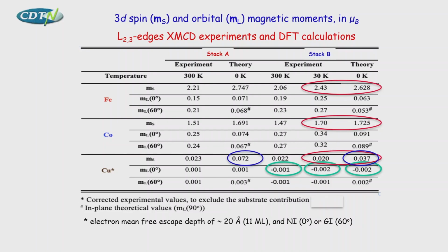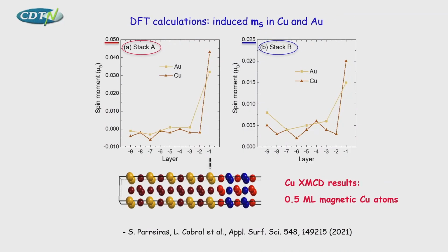That means we cooperate with the theoreticians from Campinas, and we are able to do the theoretical epitaxial growth. We got all these numbers, but the important thing is that only from the calculations we could show that in copper, for example, the magnetism happens only at the very interface, because the copper 3 gold has an interface. The first layer is always a layer that has 50% copper, 50% gold.